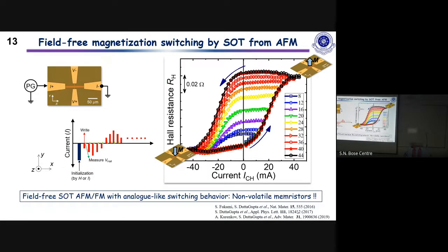This is the applied electrical current up to which this loop was swept and then came back. So this is 12 milliamps. Depending on the size of your current, you can have different resistance states. Generally you have a binary behavior where you sweep current, you go from down to up and then from up to down. But here, if you go up to this current and then make the current zero, you can stabilize your resistance. Then when you apply the current here and make it zero, you can stabilize your resistance, like that. So how is it related to your domain?